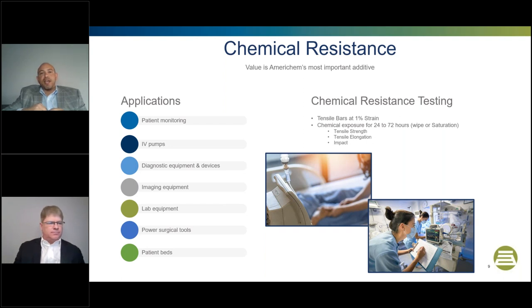And we're going to saturate a cotton ball, put it in the center of the tensile bar for 24 to 72 hours. There's the saturation test, and there's also a wipe test, depending on what the application calls for. And then after exposure time, we're gonna take that tensile bar out and we're gonna do tensile strength testing, tensile elongation, and also impact testing.